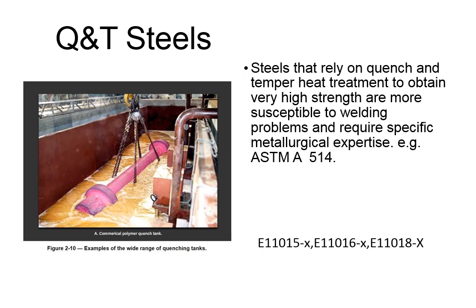So when I was telling you back when, to me it's a red flag, 80 and 90. I really start to go into overdrive when I see the tensile strength of my filler metal needs to be 110. So it just means it's weldable, but you just got to be careful and follow the rules. So it's not something to dabble in lightly, but it can be done. Do some research, dig through the American Welding Society welding handbooks, and do a Google search on welding this stuff, and you can put together a pretty solid welding procedure in no time. But just realize you're playing with fire here. You're dealing with a material that you should handle with some care and some level of expertise.